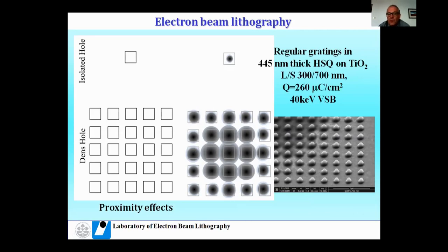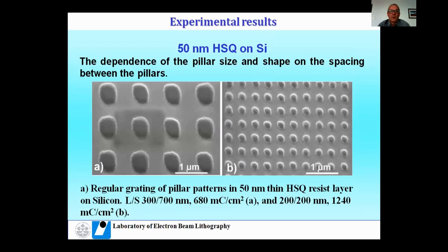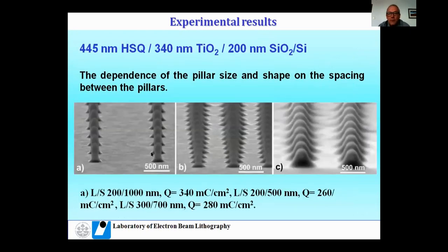So our main work is to correct this effect and to calculate for every spot the exposure dose which is optimal from the point of view of scattering. It is visible in the profile. For example, in this case we have vertical sidewalls, but if we decrease the spacing between these structures, then you can see the